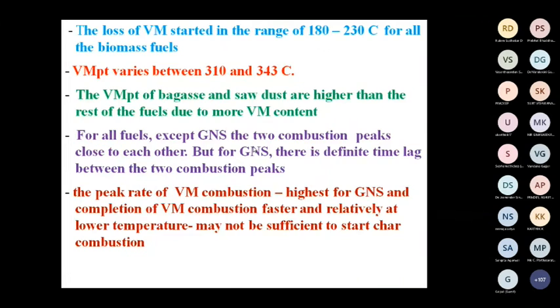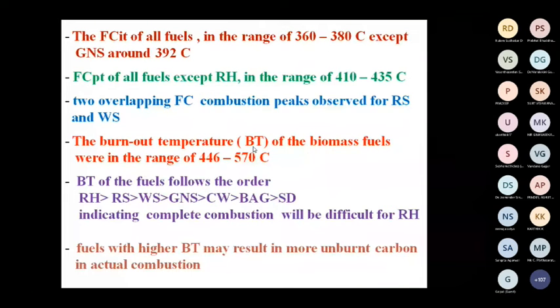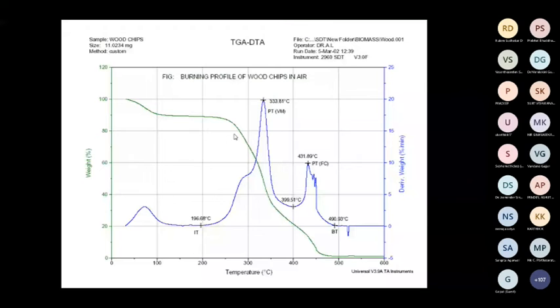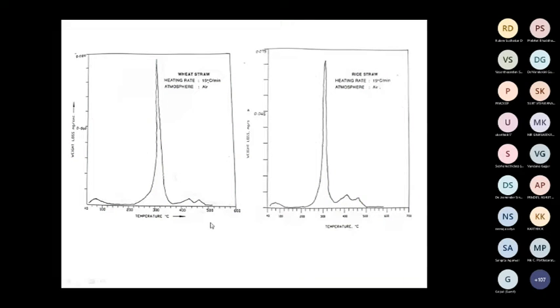The fixed carbon initiation for all the fuels is in the range of 360 to 380, except groundnut shell. The fixed carbon peak temperature for all the fuels except rice husk is in the range of 410 to 435 degrees C. Two overlapping fixed carbon components were observed for rice straw and wheat straw, as we have seen in the overlapping peaks. These are rice straw and wheat straw.